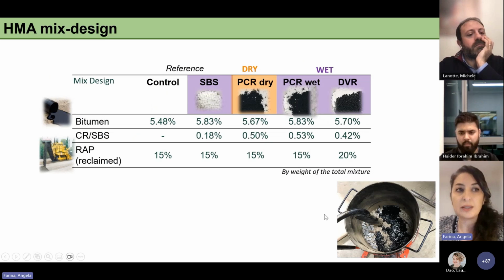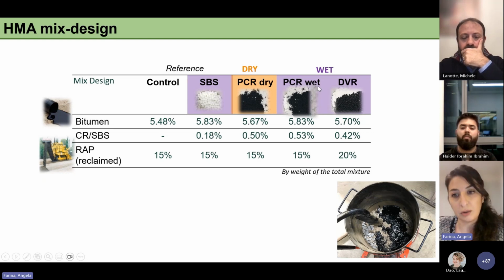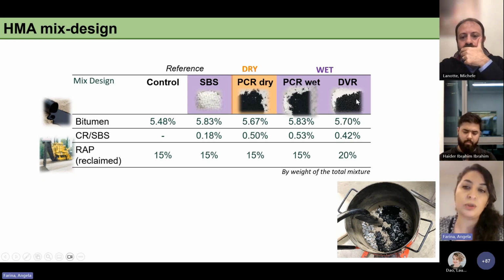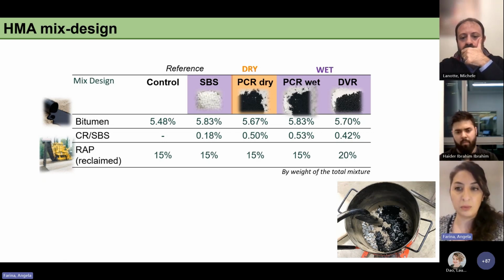In our lab at Michigan State, we designed five different mixtures. Two of them were used as a reference, so the control, the unmodified mix, and the mix modified with the SBS. Then we have the PCR developed by dry technology, so in partial substitution of the aggregates, and the PCR developed by the wet technology, modified with a small amount of SBS as well, and SASOBIT, an additive for the viscosity. And the DVR mix, where the bitumen was also modified with the DVR and a small amount of SBS. All the mixtures contain between 15 and 20% of reclaimed asphalt pavement.